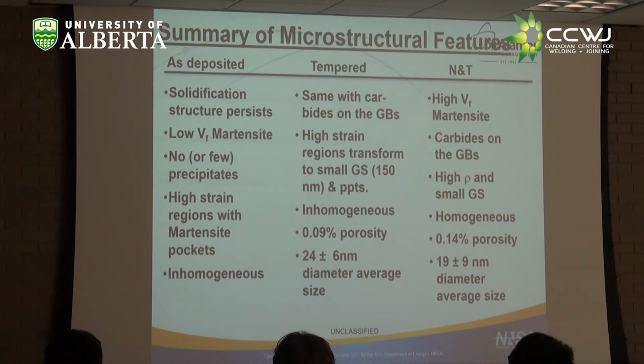So to summarize our microstructural features of the three different conditions, the as deposited condition, this is the big puzzler here. The solidification microstructure largely persists. There is a low volume fraction of martensite in those speckled regions where we saw the lathy structure in the SEM micrograph. There are few or no precipitates. There are little pockets of martensite, and the microstructure is inhomogeneous. The tempered looks just like the as deposited, except with a lot more carbides.